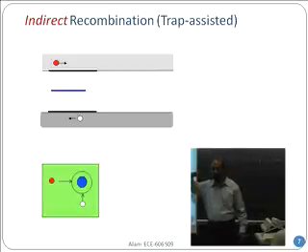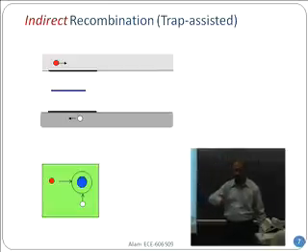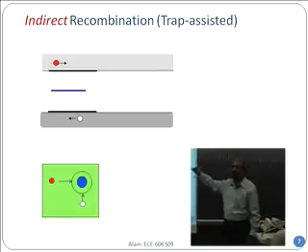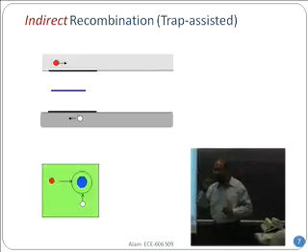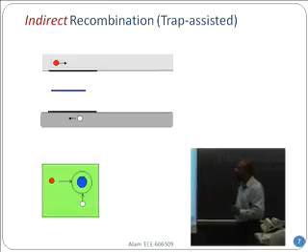If you are close to the conduction band like a donor, or close to the valence band like an acceptor, then they will give away electrons, donors and acceptors, but they cannot help you in terms of recombination. So I will call a trap a material that gives a band gap level in the middle of the gap. For example, copper or gold in silicon, which has a mid gap state, and that's what will be called a trap that can help in this recombination process.